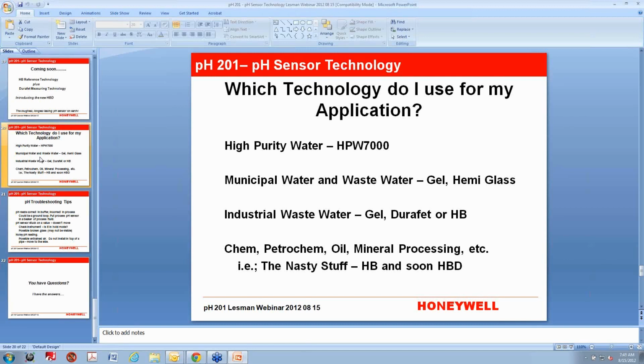If you're in municipal water or wastewater, a gel-filled reference works great. Those are very mild applications. Hemispherical glass is good because it gives you the most active sites, and they're not real challenging. For industrial wastewater, a gel works pretty well with a DuraFet or an HB, either one of those. It just depends on what's in the wastewater. Some industrial wastewater has hydrofluoric acid in it, and I've had industrial wastewater that started at -2 pH. It was pretty nasty stuff.